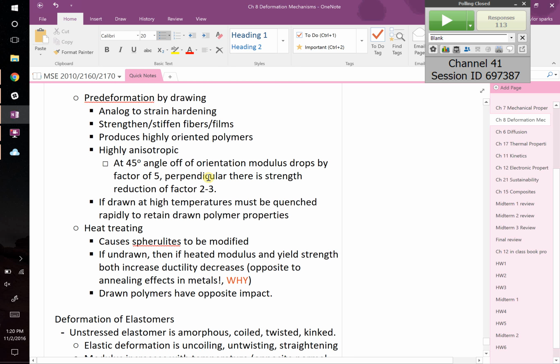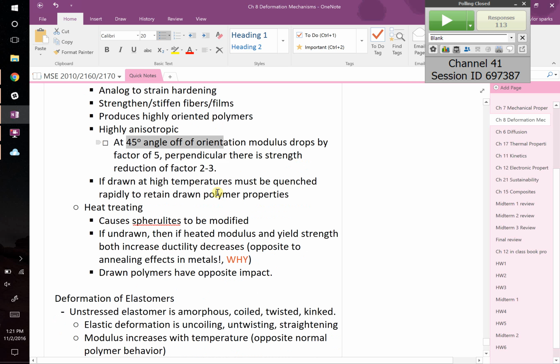It's going to be less ductile as well, right? So it's just like strain hardening, right? It strengthens them. It produces oriented polymers. These are obviously anisotropic. If you draw a polymer this way, you're going to have a lot of strength in that same direction. And transverse to that, you're going to have a lot less strength, right? And it can be pretty significant. If you, for example, take something that's oriented and then you pull 45 degrees off of that, you could see strength reduction by factors of maybe 2 to 3, right? Pretty huge drop in strength.